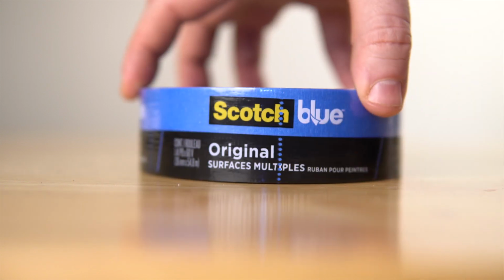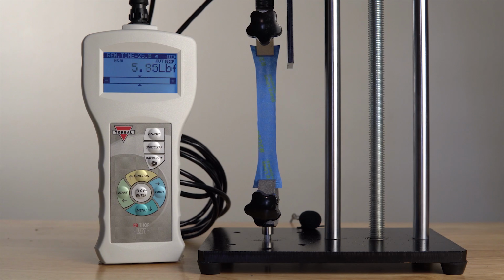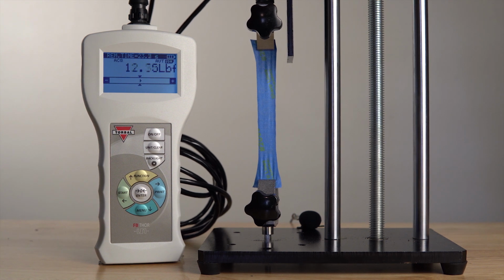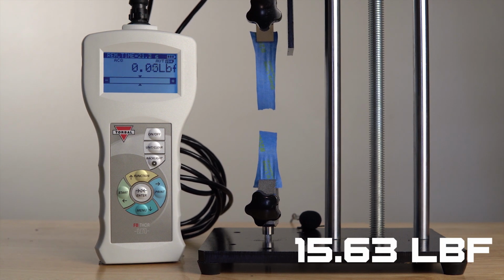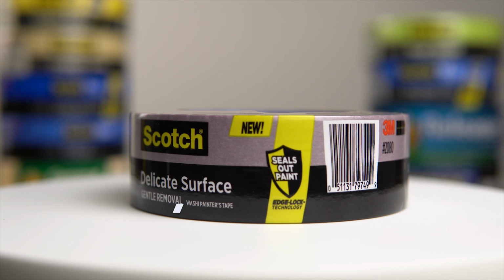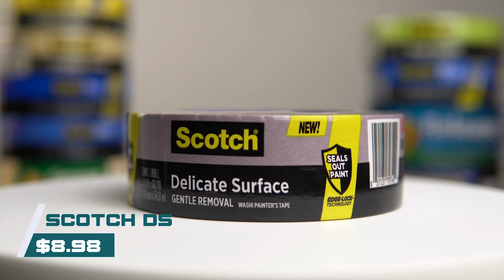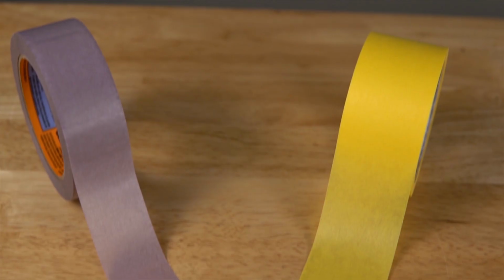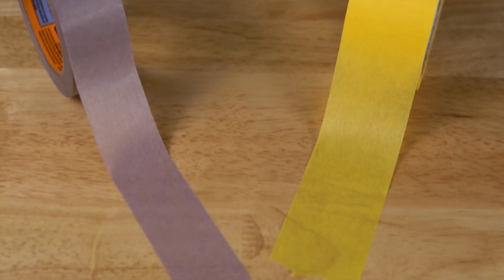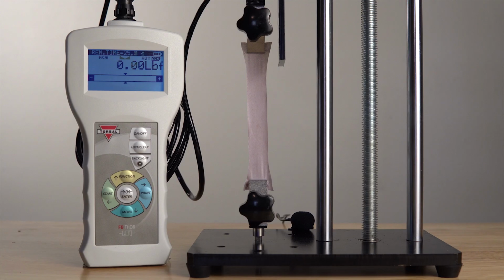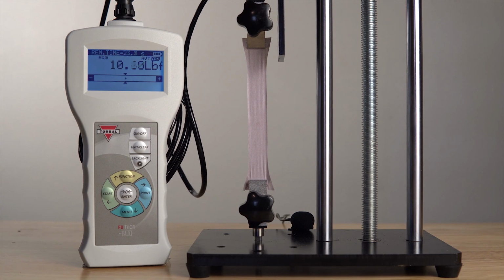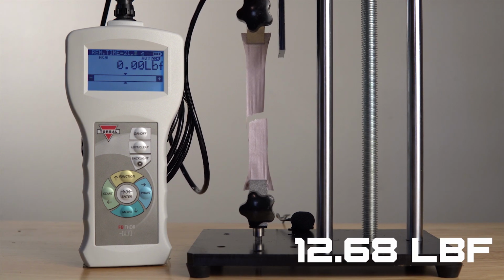It's made from a very similar material to the original, but with Edge-Lock technology. The average max tensile strength comes in at 15.63 pounds of force. The Scotch Delicate Surface comes in at $8.98 or 5 cents per foot. It appears to have a very similar material to frog tape Delicate Surface. And it shows because the tensile strength is 12.68 pounds of force.